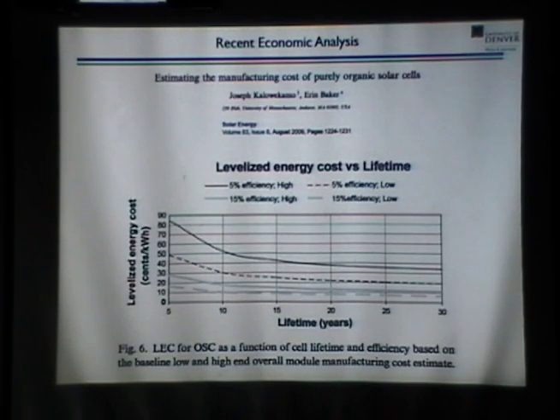Well, this study showed that essentially one does not need extremely long lifetimes to have a low LCOE. So the conventional wisdom is that you need a 30-year lifetime to get these low numbers. This study said, no, you don't need quite such a long lifetime. As long as you hit about 10 years, then the slope of this plot flattens out a little bit.